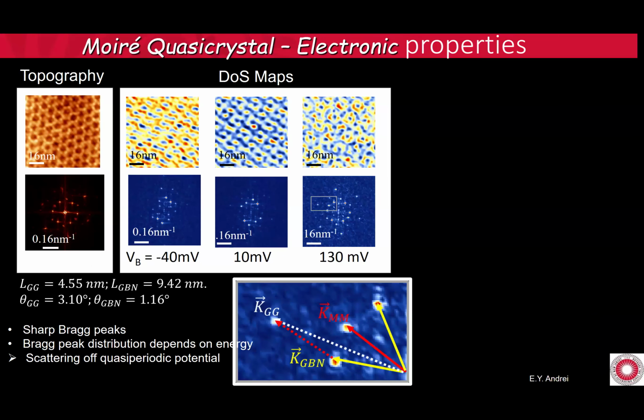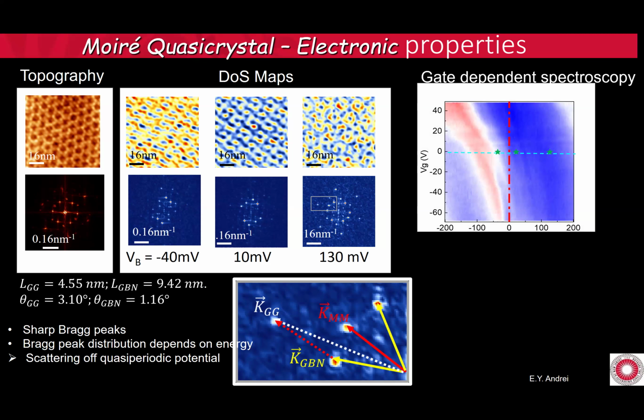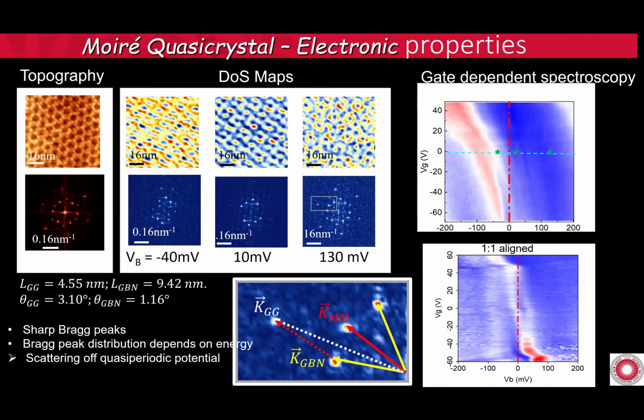And then finally, we go to the quasi-crystal, again, the same thing. Which Bragg peaks light up depends on the energy. And here you see the dodecagonal symmetry, the 12 peaks. And you see again that they come from a linear superposition from the KGG and KGBN. And now the band structure looks even more different. And here I'm comparing it to the perfectly aligned one. So very, very different behavior with just tiny changes in the twist.